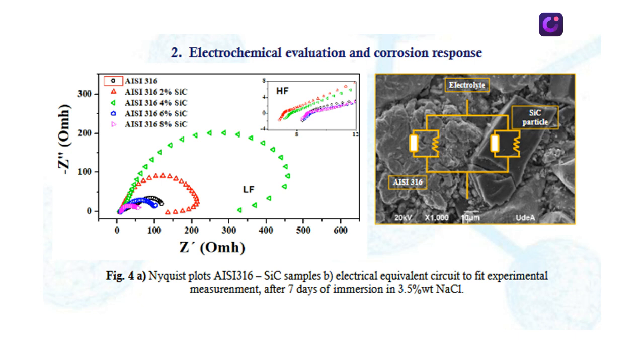The materials then show the conformation of a parallel equivalent circuit where two time constants are present, with the resistance offered by the steel and the resistance presented by the acicular silicon carbide particles. Therefore, the electrochemical behavior is dominated by the permeation capacity of the electrolyte into the materials through the pores left after the sintering process.